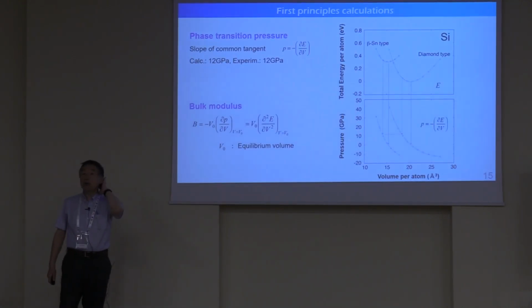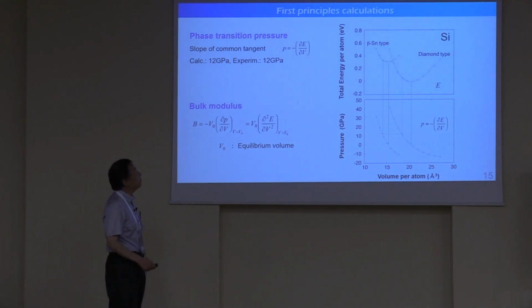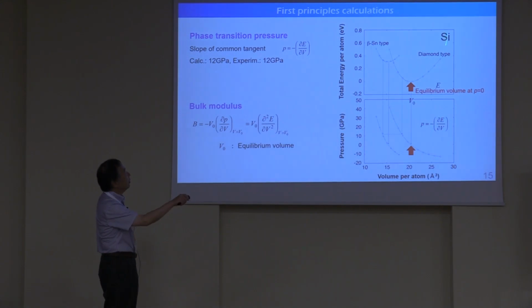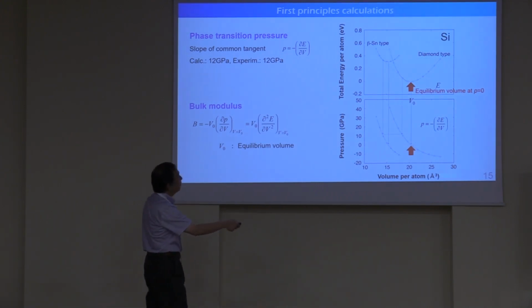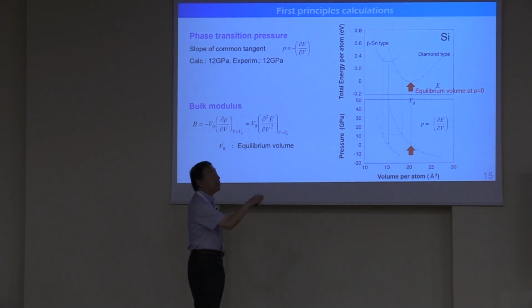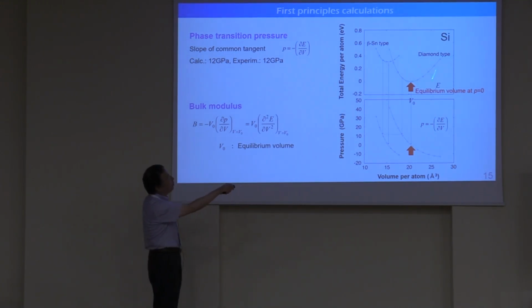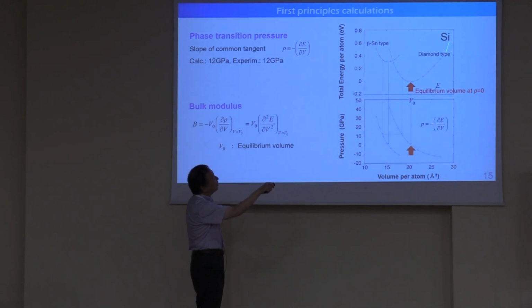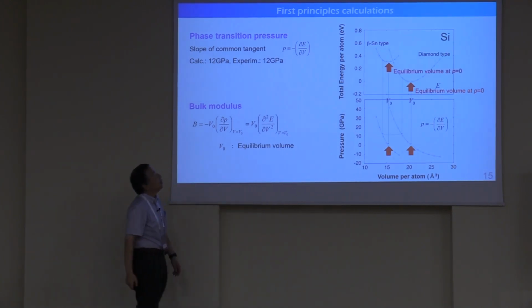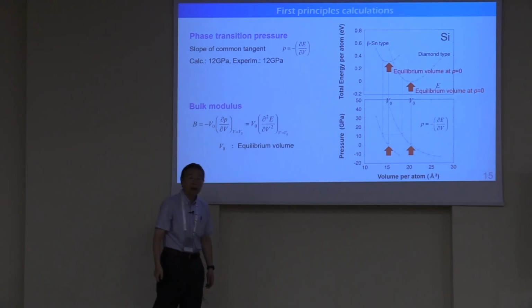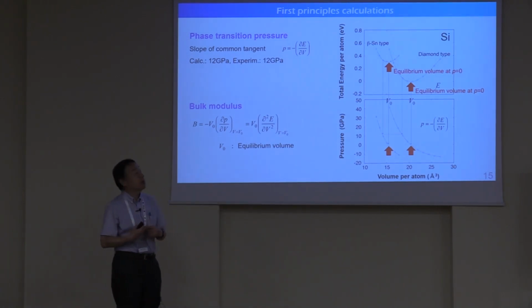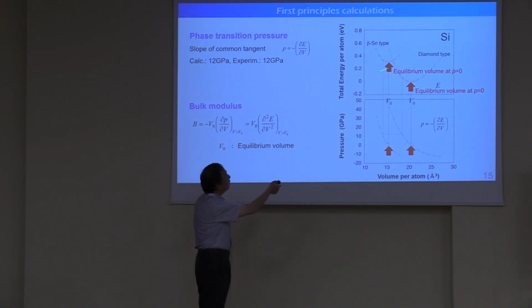Also, by the first principles calculation, you can obtain many different properties. For silicon, if you compare diamond, equilibrium volume is here. This is the volume versus the total energy. So if you make structure optimization, you can end up with the volume here. But also, by changing the volume, you can have this type of curve. If you also perform calculation for beta tin type, which is a higher energy structure of silicon, you can have another curve on volume versus energy curve as shown here.